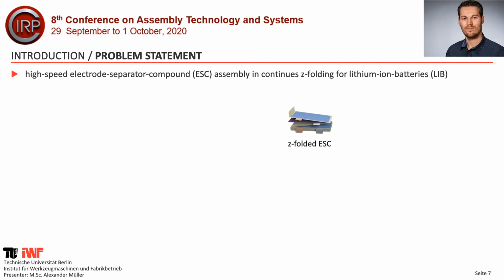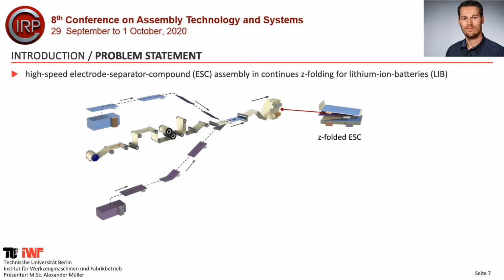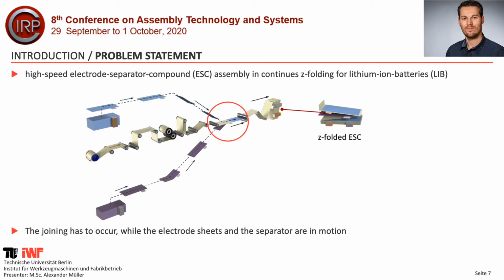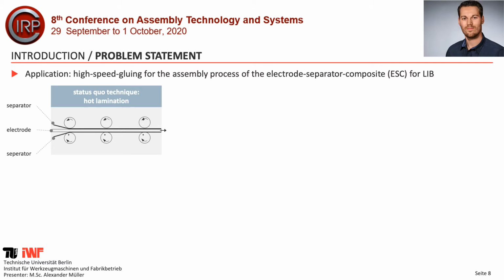So my colleagues and I developed a continuous Z-folding process, and for this process we need a joining process where we join the separators in motion, and this is why we need a really fast joining process. Normally if you want to join electrodes and separators, you use a hot lamination process with a material speed of a maximum of 400 mm per second, but there are some problems.